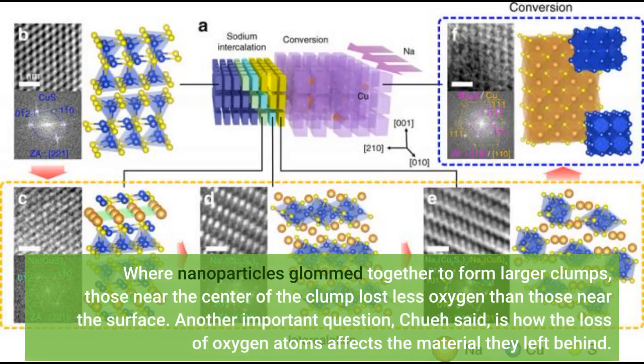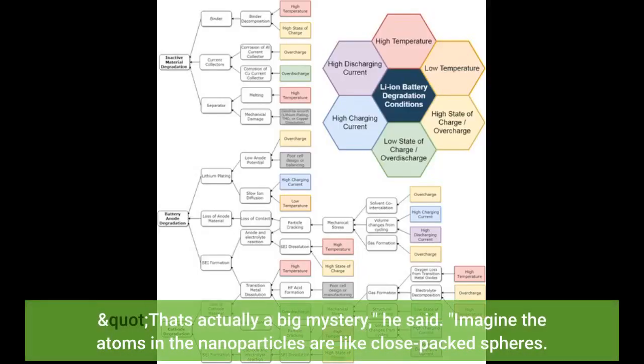Where nanoparticles glommed together to form larger clumps, those near the center of the clump lost less oxygen than those near the surface. Another important question, Chueh said, is how the loss of oxygen atoms affects the material they left behind. "That's actually a big mystery," he said. "Imagine the atoms in the nanoparticles are like close-packed spheres. If you keep taking oxygen atoms out, the whole thing could crash down and densify, because the structure likes to stay closely packed."